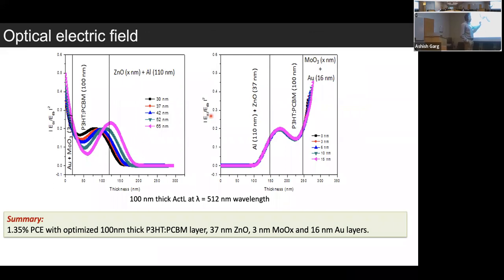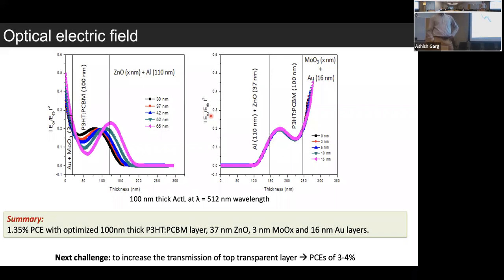What we see is when you plot the optical electric field in the device as a function of thickness using a transfer matrix formalism, for certain thicknesses the idea is to maximize the optical electric field within a layer, because that is good for solar cell characteristics. We find that for the chosen thicknesses, the optical electric field is maximized in the device. For example, zinc oxide works out well at 30 nanometers; in other cases the field goes down. In the case of molybdenum oxide, all the thicknesses work well, but practically speaking, 3 nanometers works better than other thicknesses. The problem is we still have lower transmission.